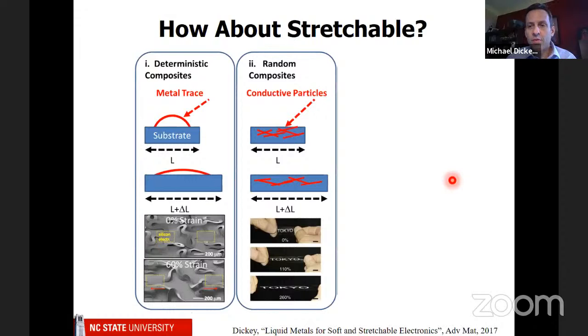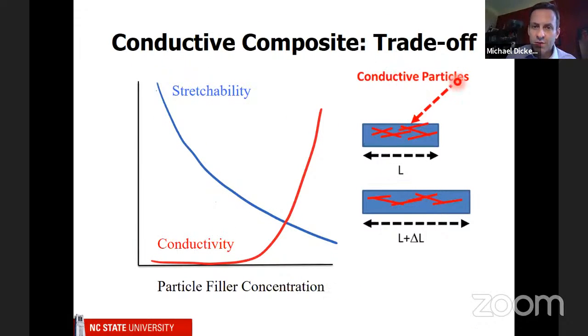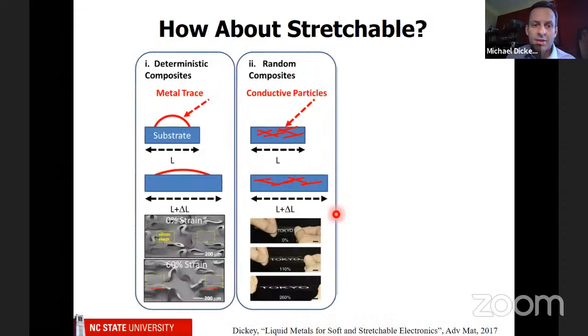Another approach, if you want to make a stretchable conductor, is you can take conductive particles and put them into a stretchable material. So when you stretch it, the conductors maintain their conductive path, and this actually works quite well. But there is one trade-off here. As you put these conductive particles into the elastomer, first of all, you need a lot of particles so that they have a conductive path, so that the electricity can go through. To get your conductivity up, you have to add a lot of filler. And the more filler you add, the less and less stretchable it becomes. So this is a trade-off with this composites approach.